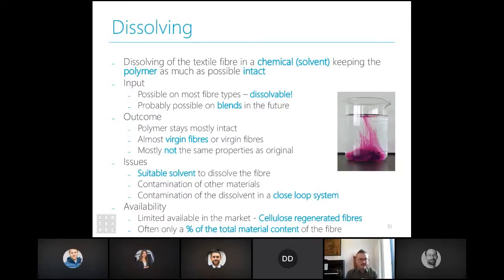I told you already that the polymer stays mostly intact. You get, as an end result, almost virgin fibers or virgin fibers. And in most cases, so not always, but in most cases, you get a different fiber. Think about when you start from a cotton fiber and you end up with a lyocell fiber.